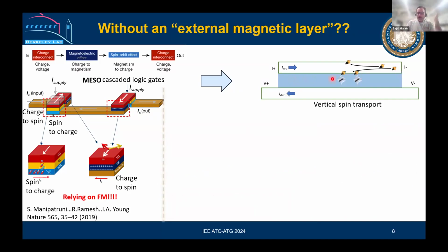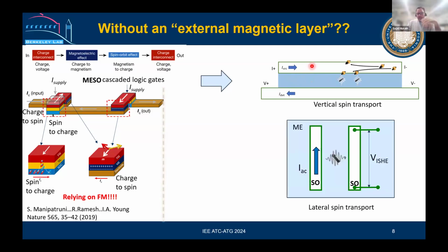We use a magnetoelectric material in the middle, and we use a spin orbit coupling material on the other side. So we're not using any more ferromagnet. What we're doing is trying to play with the bismuth ferrite as a magnetic medium to increase the output voltage, or to bring this system into the real world. And for more simplification, we are just using this whole device as a non-local magnon transport device, a conventional magnon transport device.